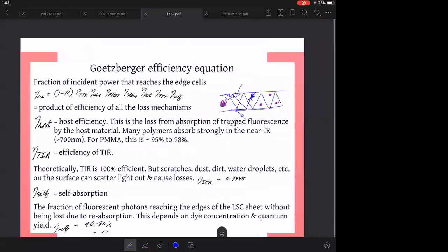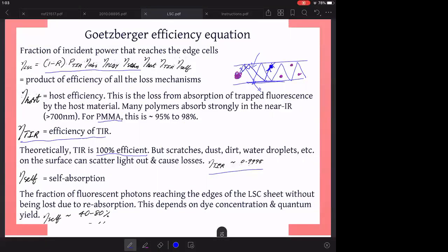And that loss is actually the reason why you cannot arbitrarily increase the concentration factor. The larger you make the window, the longer the emitted light has to travel to reach the solar cell. And the longer it travels, the higher the probability that it will be absorbed by other molecules in the host matrix. This is why you cannot beat the second law of thermodynamics using this approach, which, if you are a very astute observer of these lectures, you might have asked that question. In any case, that's a very interesting point by itself.